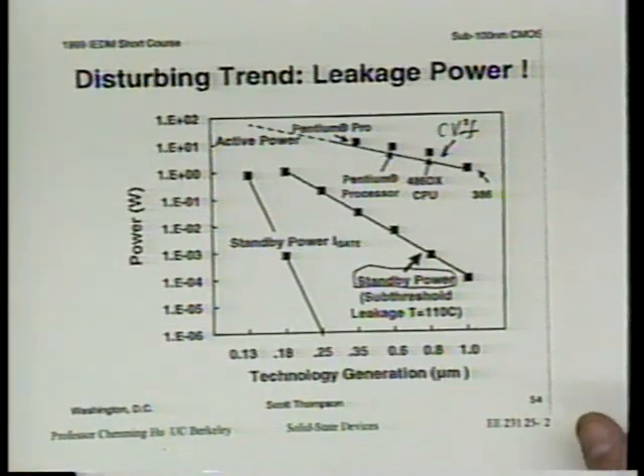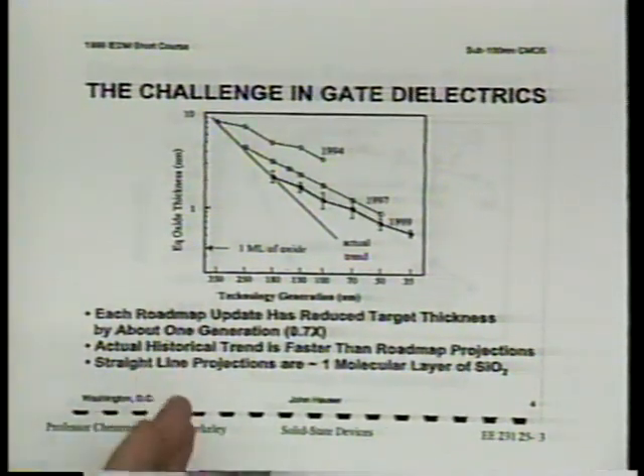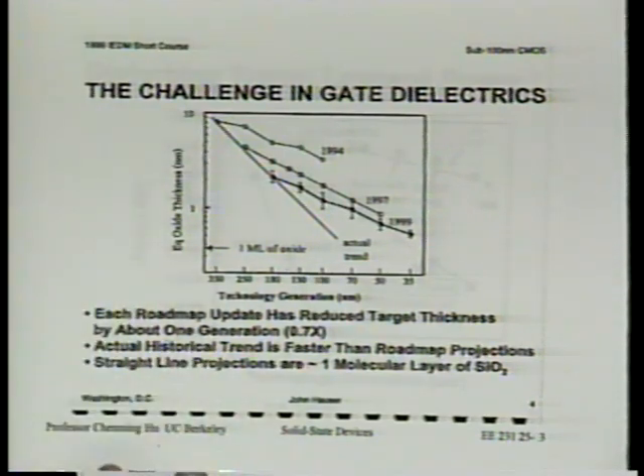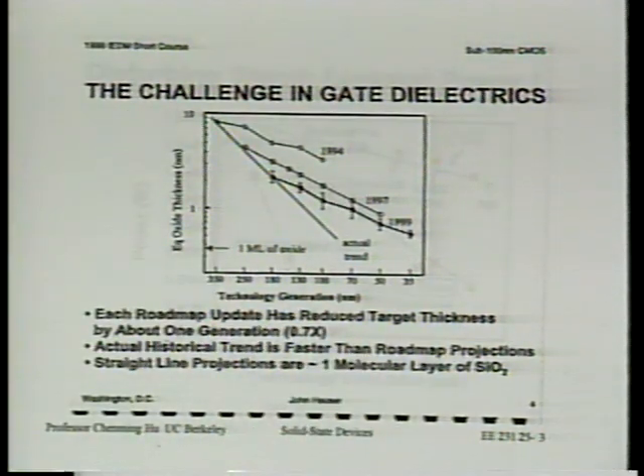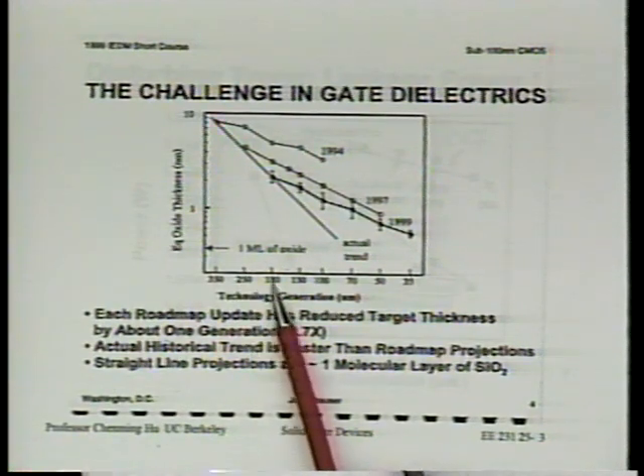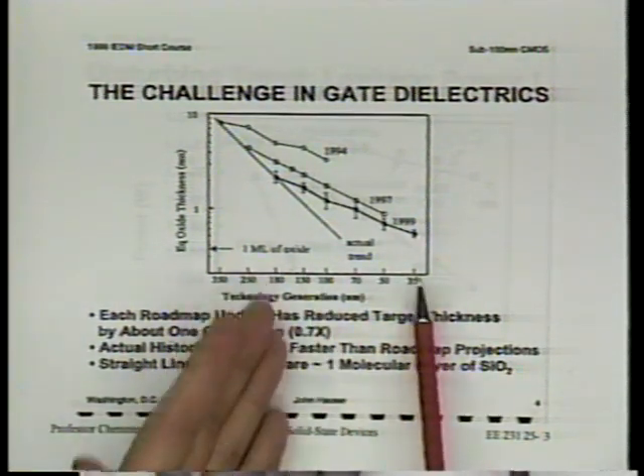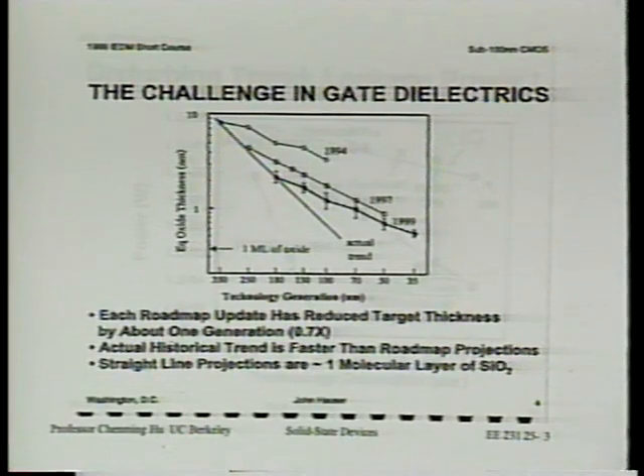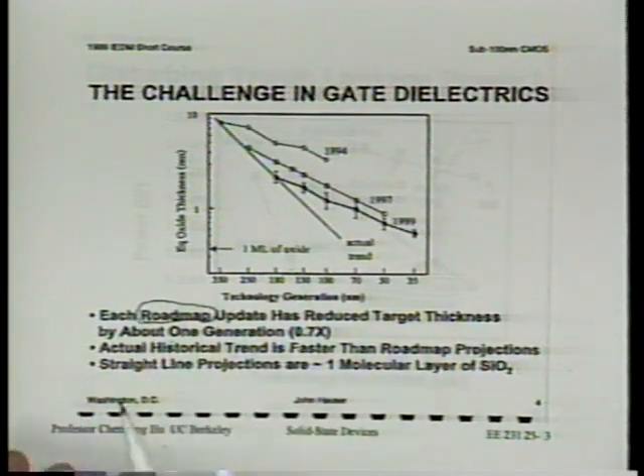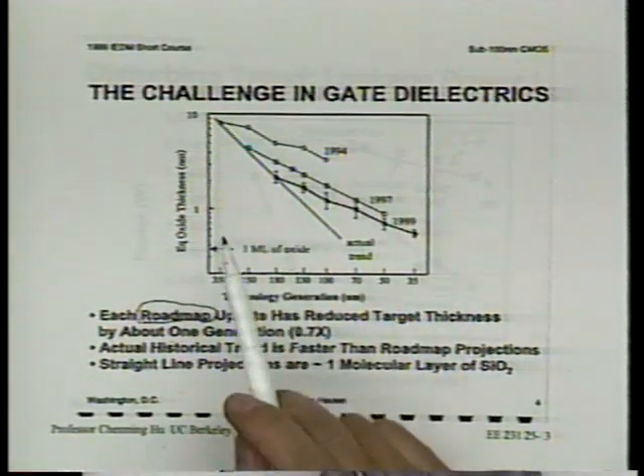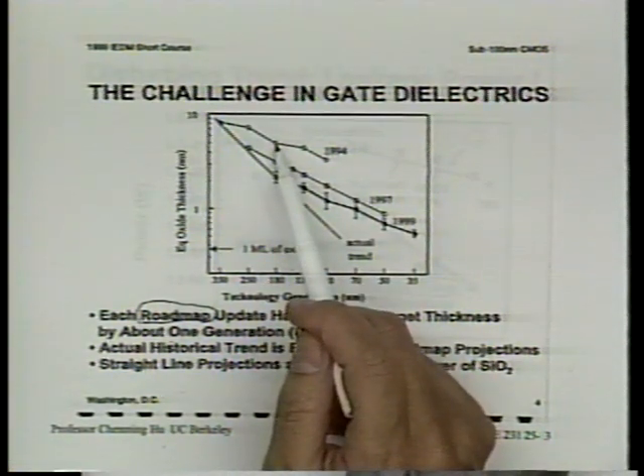People found they could do better than expected, or they negotiated with product engineers and found they could tolerate more leakage. The scale here is 100 Angstroms down to 10 Angstroms. Actual practice has beaten the projections. At 12 Angstroms, you're going to get 100 amperes per centimeter squared at one volt — very alarming.